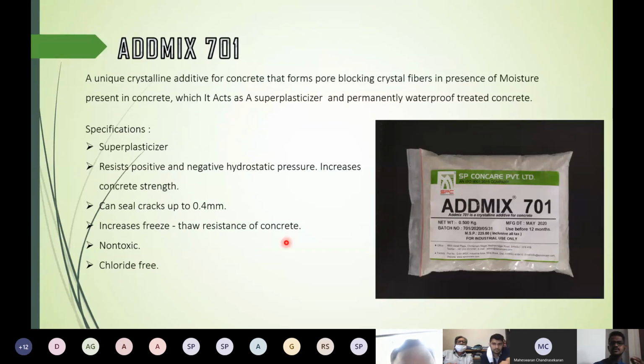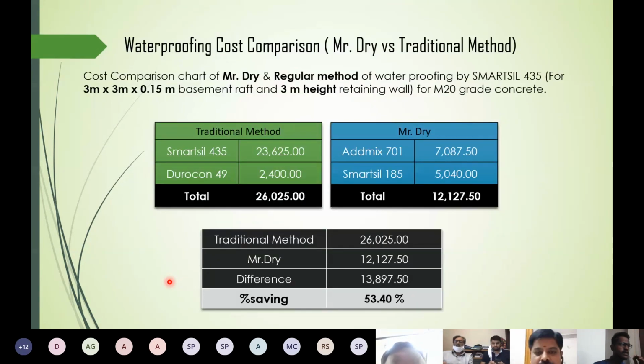So there are many specifications of this particularly unique admixture. What are the specifications? It is a super plasticizer. It resists the positive and negative hydrostatic pressure and increases the concrete strength. It can seal cracks up to 0.4 mm. It increases the freeze and thaw resistance of the concrete. It is non-toxic and is also chloride free. Using this Addmix 701, we have developed a new system, that is the Mr. Dry system, which is used during the construction to make your concrete waterproof.